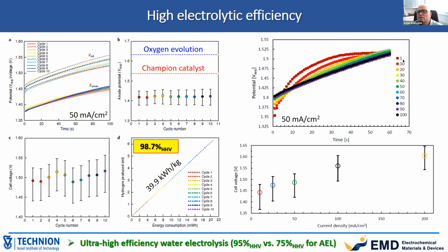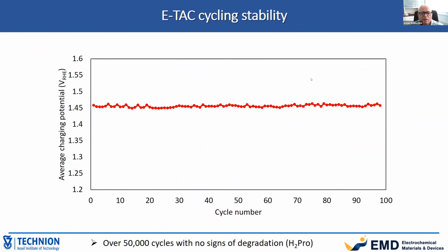And here you can see cyclability. So these are 100 cycles. You see that there is some change from the first to the 10th cycle because the system is just breaking in, but then the next 90 cycles are completely reversible. And here you see after a while, when we do multiple cycles, they are completely reversible. At the company, they already tested many tens of thousands of cycles. So this reaction is totally reversible.